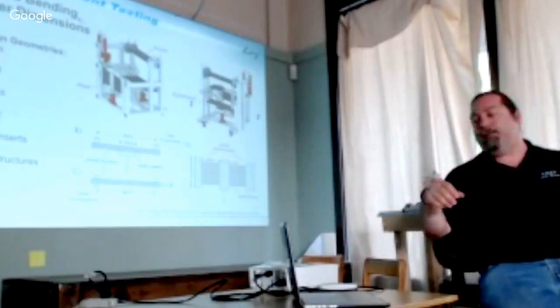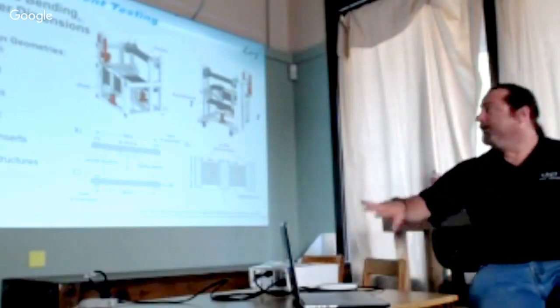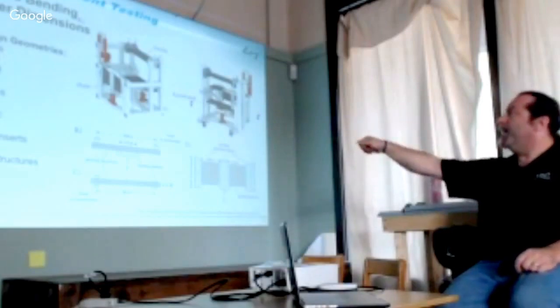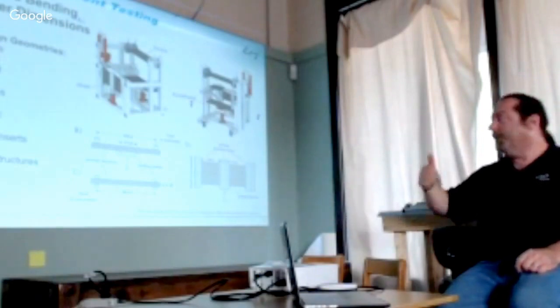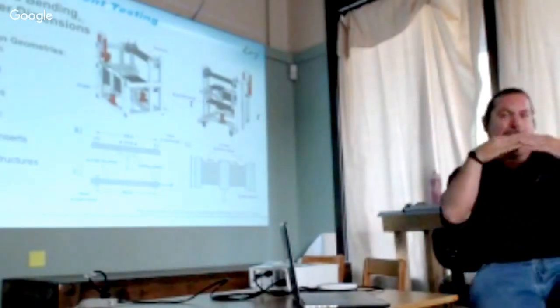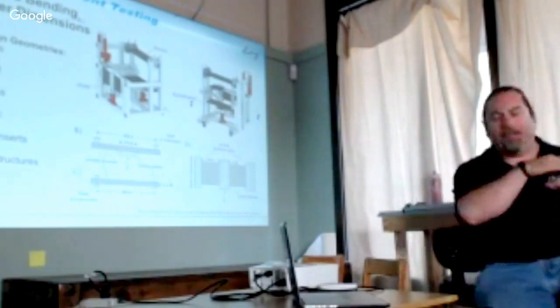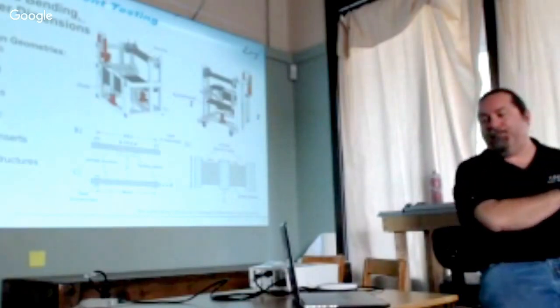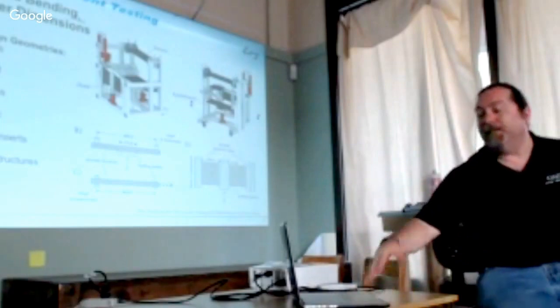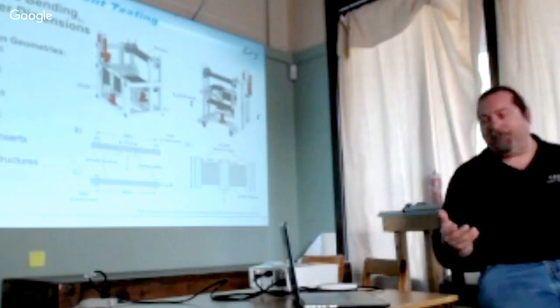We devised this 1 foot by 3 foot box shape outer dimension, and we're loading it in torsion, shear, and bending. We built this test rig that has torsion, shear, and bending fixtures built into it. It just uses hand jacks, but it has load cells and linear LVDT for displacement measurement. We also use digital image correlation to determine the full field strain of the specimen during the test. The geometries included increasing wall thickness, vertical prints versus flat prints, increasing densities of infill, some different manual infill patterns, and various surface textures. I'll show some photos of that, and then the reinforcement methods: the overwrap method, filling it with foam, and things like that. We actually inserted steel bars in some samples too.